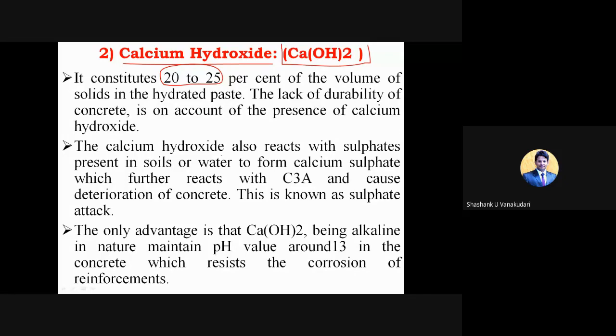And then the calcium hydroxide also reacts with the sulfates, that is Ca(OH)2 reacts with sulfates like SO3, which is present in soils or water, to form calcium sulfate, which further reacts with C3A, and that causes the deterioration of concrete. Deterioration of concrete means it reduces the quality of the concrete. That is because of this calcium hydroxide. As you can see at the top, calcium hydroxide reacts with the sulfates and forms calcium sulfate, CaSO4. That calcium sulfate further reacts with C3A, and that causes the deterioration of the concrete, meaning the concrete loses its properties.